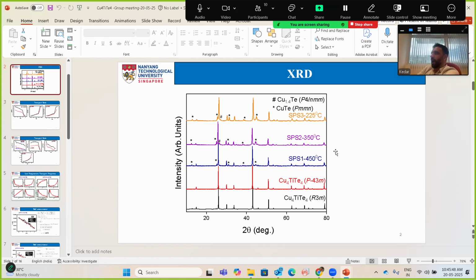That's what Jayanta said in the beginning. Now, the point I'm making: how do you know that 500 degrees Celsius and the SPS pressures may not give you an even better sample? You haven't reached the point where it decomposes yet. Why don't you try that? I think you should do that experiment anyway. The goal is clear, right? You do in-situ XRD, work with Ivan, get the powder samples done, look through the step-by-step phase composition analysis, and then try 500 degrees Celsius.